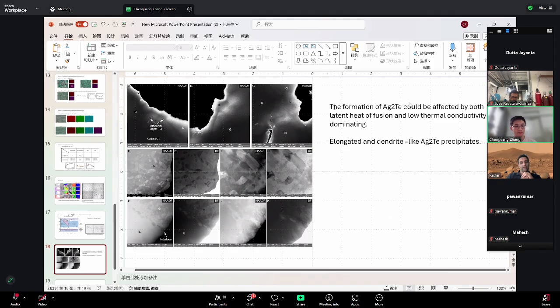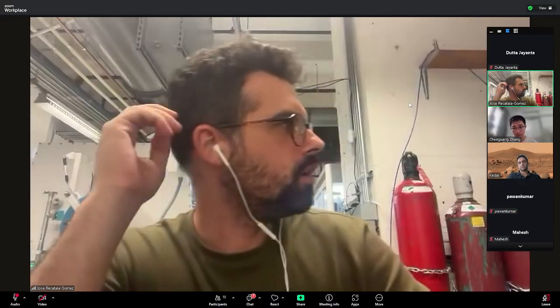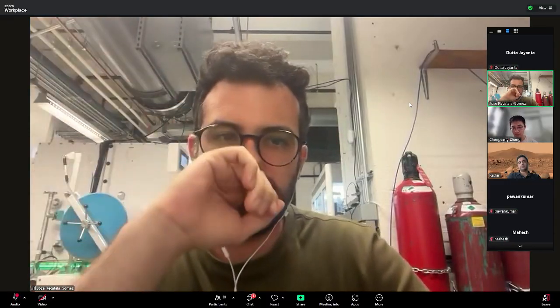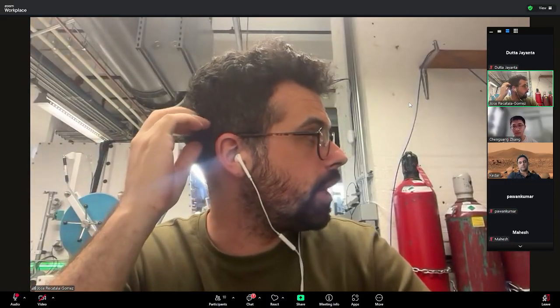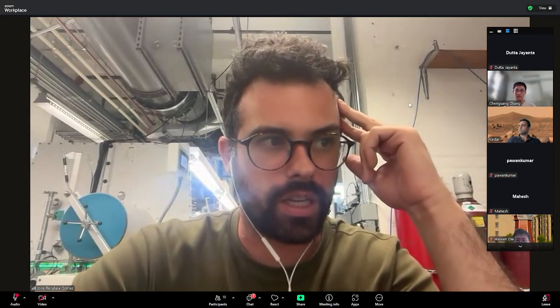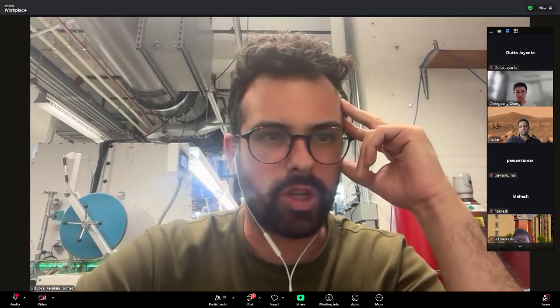I don't know if you have a fast XRD. Who has a fast XRD? What is the fastest cooling rate in the XRD in A lab, Pepe? So if you do it in air, it's pretty fast, because you basically have it open in the chamber, so it would be close to air quenching. But normally we do the experiments here in nitrogen, and then the cooling rate is much slower.